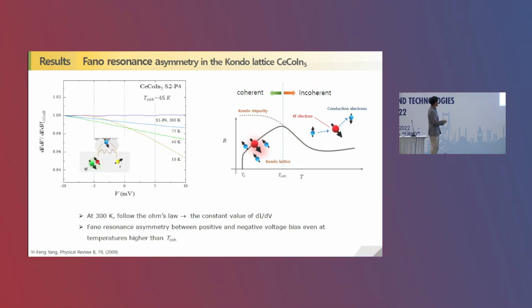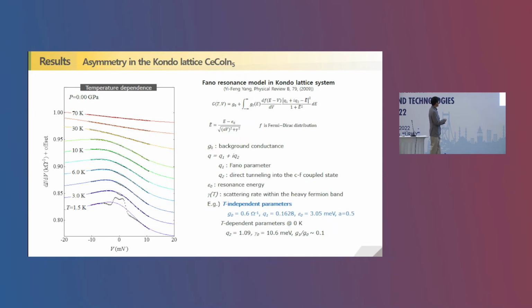So this is differential conductance as a function of bias voltage at high temperature. The purple line is at 300 Kelvin, which is pretty much flat, as expected, because it follows ohmic behavior. And then with decreasing temperature, you can see that the conductance curve shows an asymmetry between negative and positive bias voltage. We note that the coherence temperature, which shows a peak, is around 45 Kelvin, and the temperature where you start to see the asymmetry is higher than 45 Kelvin. So this is the temperature dependence.